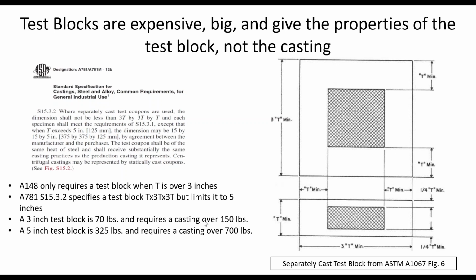A 3-inch test block is 70 pounds, and I have to put risers and gates on it, so it weighs over 150 pounds. So if I have a 1,000-pound induction furnace and you want a 3-inch test block, I'm using 15% of the heat to make the test block. A 5-inch test block is 325 pounds. And so you can see right away that you're going to chew up an awful lot of steel really fast if you want a special test block.